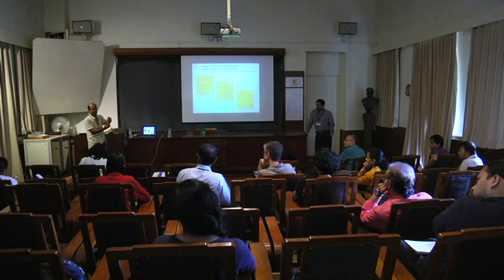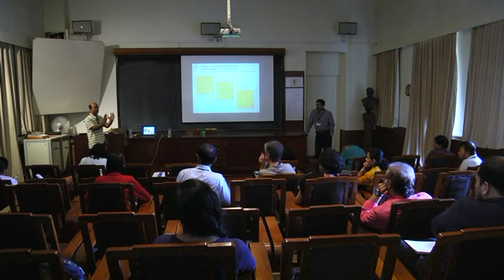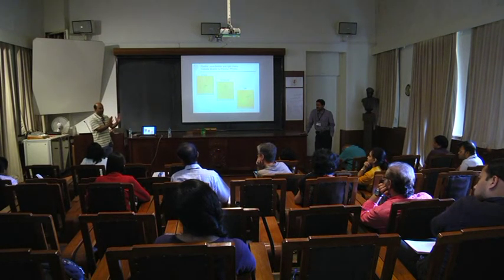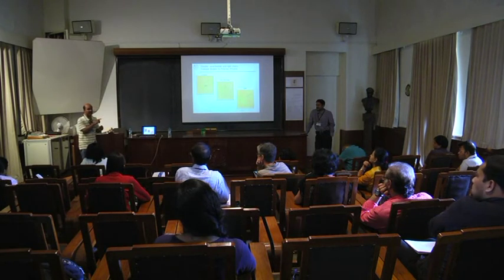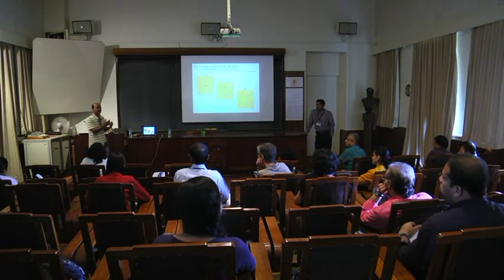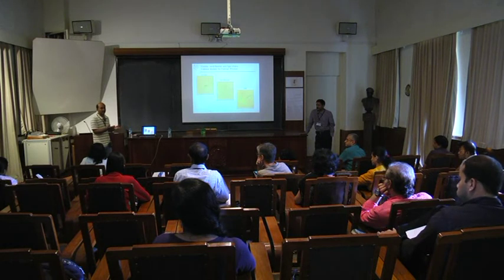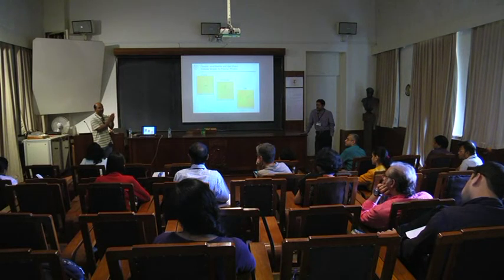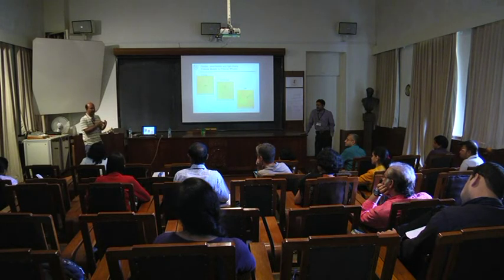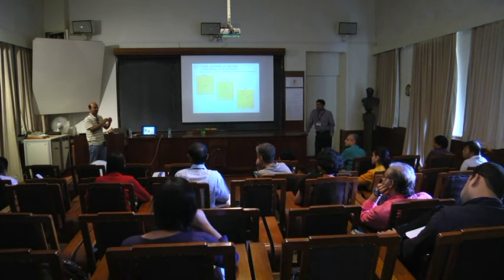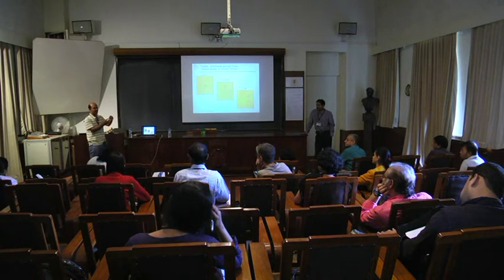So they come back to exactly the same position. They move enough so that the walls locally become fatter. So for the overall sample, the Poisson ratio is 0, but I think that's really because the walls are becoming thicker, and that's the other reason why you have this not so steep dependence of the modulus on the bulk density, right? And then beyond about 40% compression, the walls start touching each other, and that's where the stress takes off, right? But what's crucial is that this tiny amount of organic is somehow distributing in this magical way that allows you to move past each other and come back to exactly the same position.